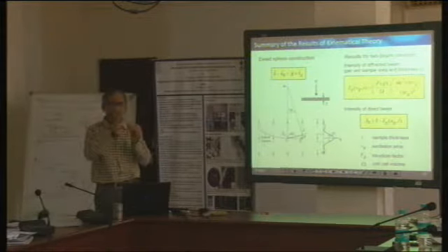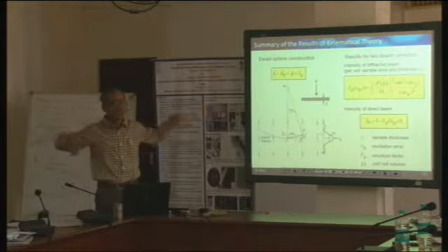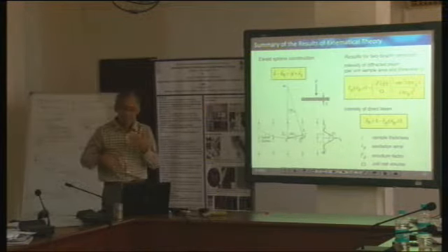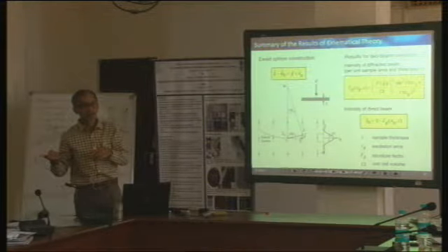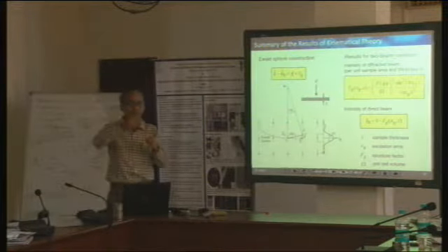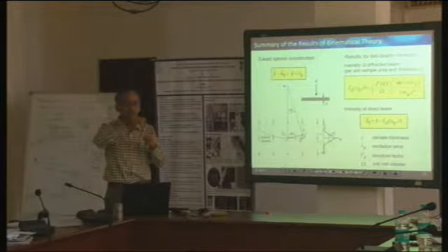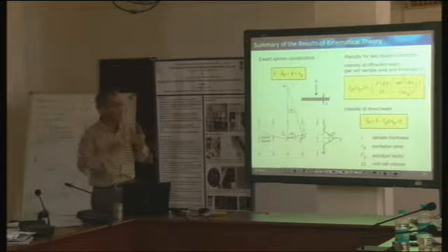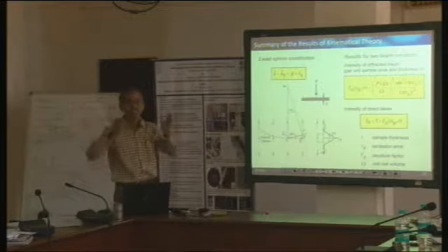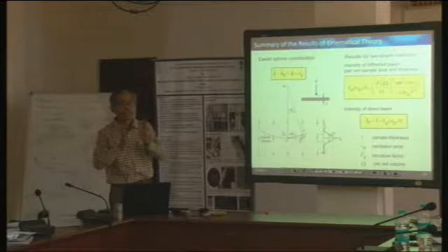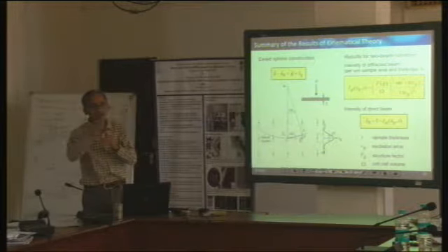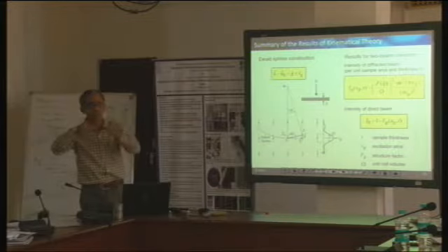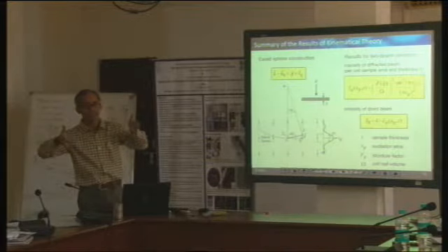These lattice points are small, but the crystal is infinite in size. If I now make the corresponding reciprocal lattice, I again get lattice points which are point objects. But if the crystal becomes finite, that is, its dimensions begin to shrink, then the reciprocal lattice points are no more ideal point objects, but they begin to increase in size.